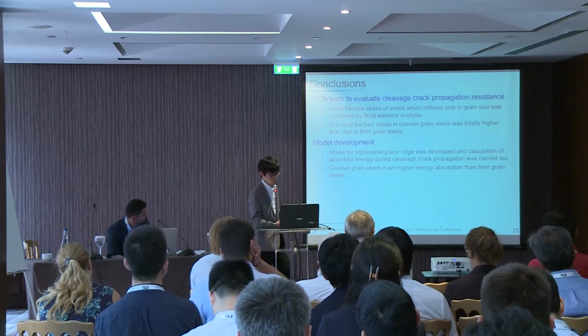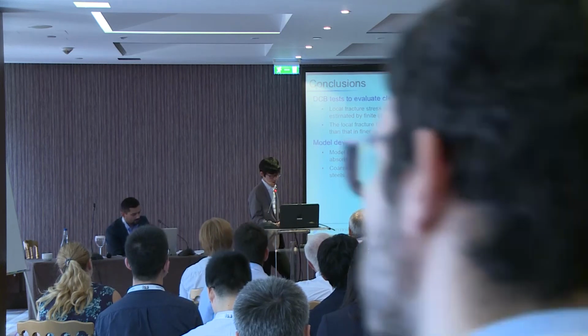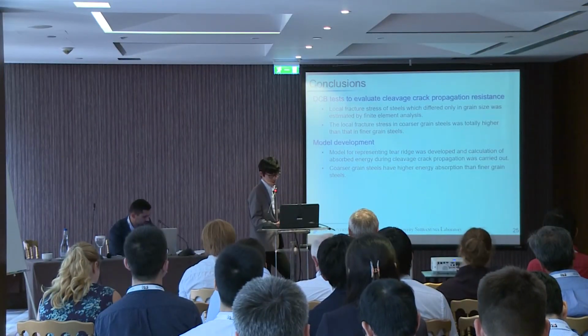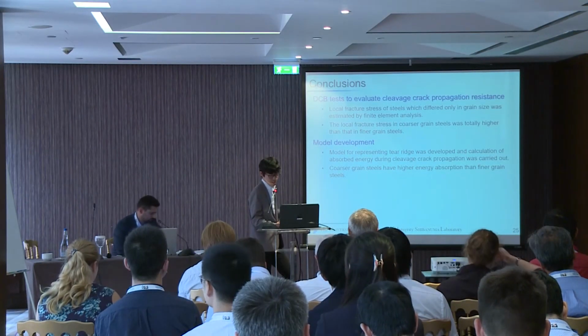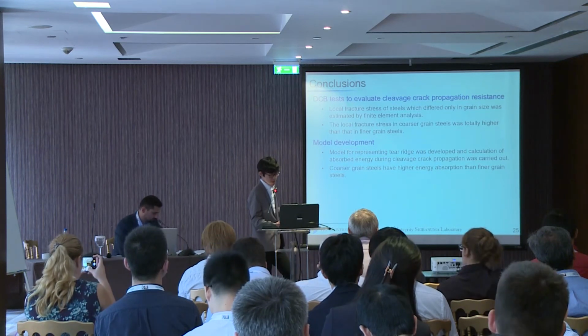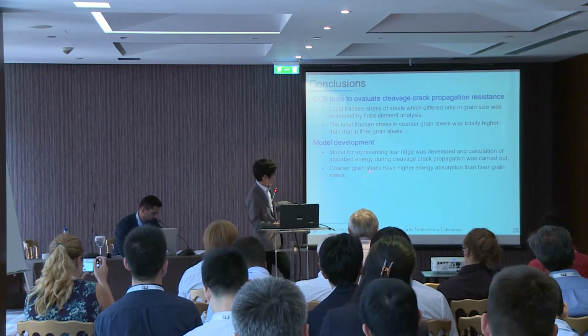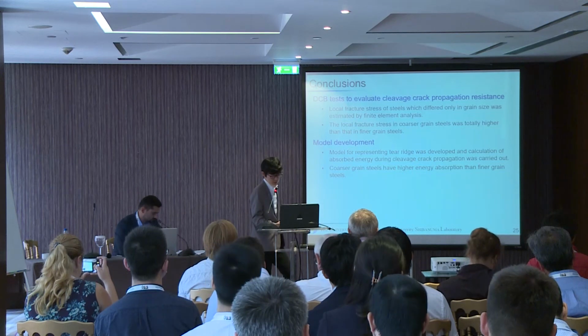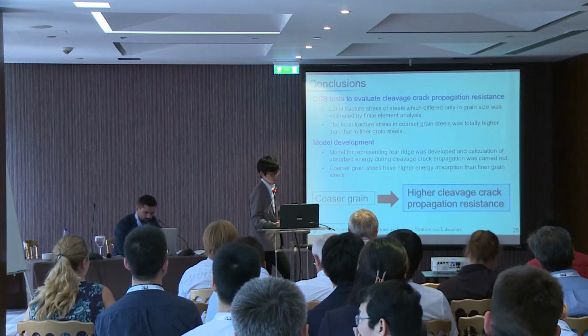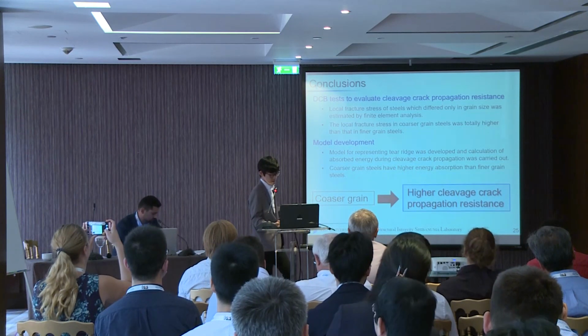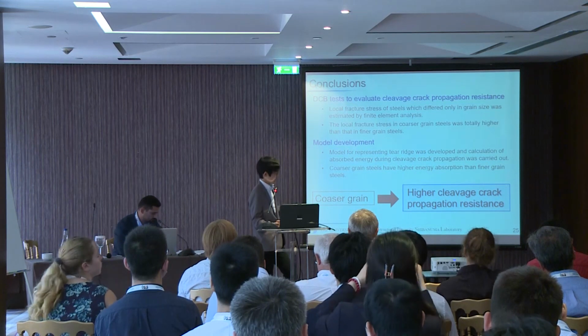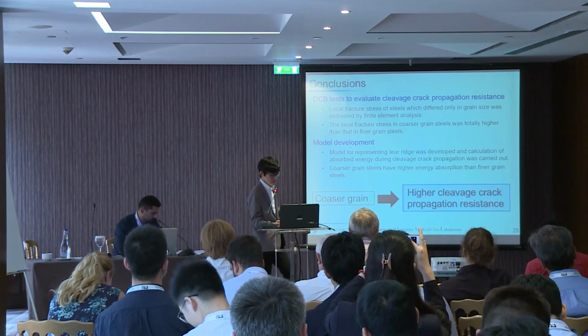In conclusion, we tried to investigate the effect of grain size on cleavage crack propagation resistance, experimentally and theoretically. And it is shown that coarser grain has higher cleavage crack propagation resistance.